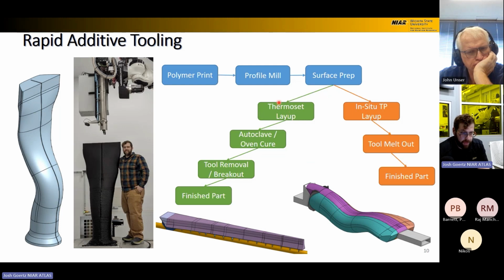Or we can also use a higher temperature 3D printing resin, where we can do an autoclave or an oven cure of a thermoset material, and then either build it in segments or break out the tool from the finished part. Or in the instance of this spar here, it's non-locking geometry.